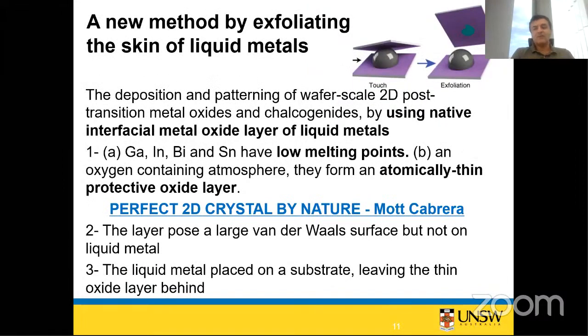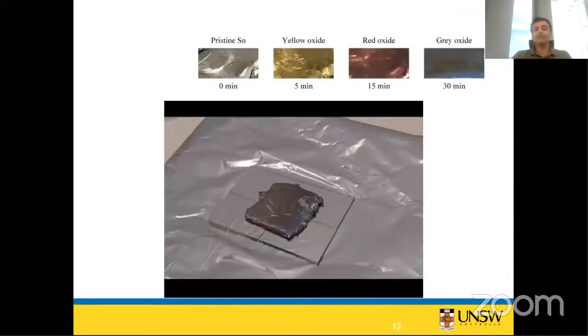When we're talking about the oxidation that happens naturally on the surface of liquid metals, the Mott-Cabrera oxidation, that means everything oxidizes at the same time. You don't get any grain boundaries. If you have gallium, indium, bismuth, tin, they have low melting points. You melt them, and on the surface you produce the oxide. You bring a substrate very close to the surface and touch it. On one side, this two-dimensional material doesn't attach to liquid metals. On the other side, it can easily attach to the substrate and you harvest it.